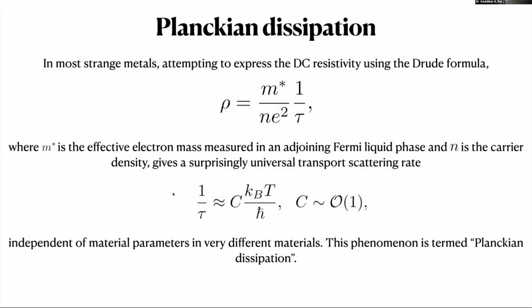Okay. Then, strange metals also tend to have this feature of Planckian dissipation, where if you're doing DC transport and trying to use the Drude formula, knowing the density of carriers, if you use appropriate effective mass that includes effects of interactions, you get a scattering rate that is order 1 number times k_B T over h bar.